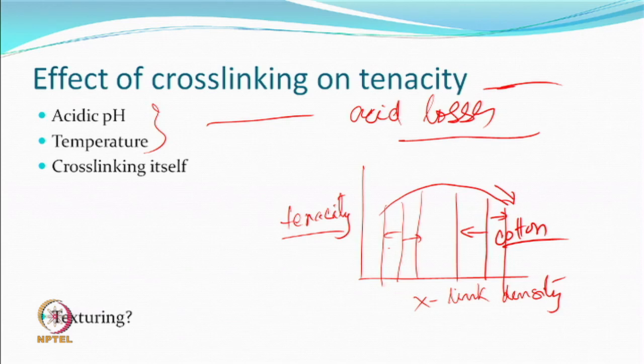In addition, the texturing. So, what is texturing doing? It is twisting first. It is not like the fabric or a fiber or a yarn is in a relaxed state. It is actually not in a relaxed state. You are twisted and you are going to be cross-linking a twisted yarn, because that is what the texturing has to be used for. This is how the texturing will be done. So, what it means is a material has been subjected to stresses and the stresses are being stored in. And so, this material will become weaker in that sense also. Who likes to be under stress? Any material under stress can fracture, crack, and so tenacity after cross-linking or let us say after texturing by this method is likely to be less.